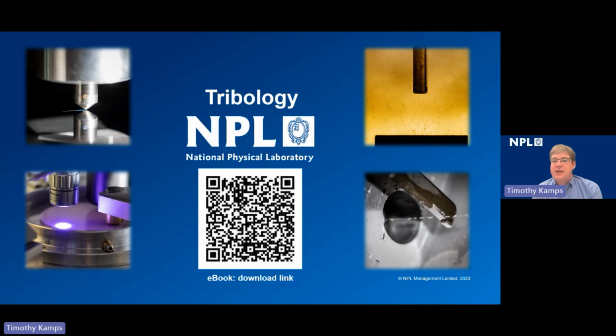So there's a question here that says, I have an application that I'd like to measure sliding friction, but it's at a much smaller scale than the equipment shown in the presentation. Do you have suitable equipment for this? Yes, one of our tribometers, the NPL micro tribometer, sort of does what it says on the tin. It's actually a tribometer that fits inside a scanning electron microscope, and we can use various end effectors with very small radii down to 1 micron and smaller to perform sliding friction and wear tests in situ in the SEM, and this gives us the ability to take high resolution images and understand wear mechanisms in greater detail.